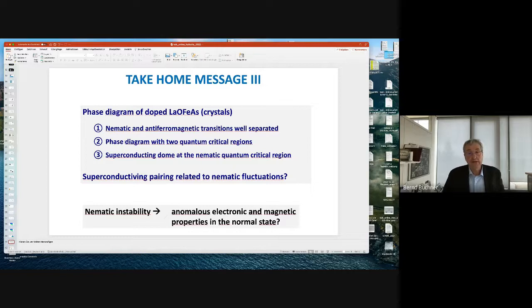We have a phase diagram with two quantum critical regions, one where the magnetism disappears and one where nematic order disappears. And the superconducting dome is clearly located at the quantum critical point where this nematic transition disappears, where the energy scale of the nematic fluctuations hits zero. And of course, this raises the question whether superconductivity is really related to nematic fluctuations.